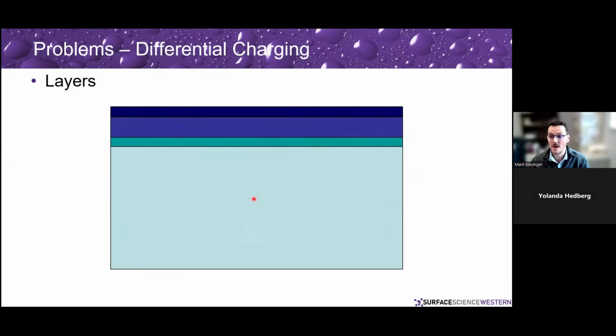So if we have like a metal surface, we've got this interlayer here that if this was a thin enough oxide, it would behave almost conductively, and you wouldn't even need to use a charge correction system on this. As that layer grows, it becomes insulative and it no longer behaves in conjunction with the metal, which is pegged at the Fermi level, right? As you put layers on top, things change. Some of these layers may not behave the same as others. And so you get this differential charging problem.